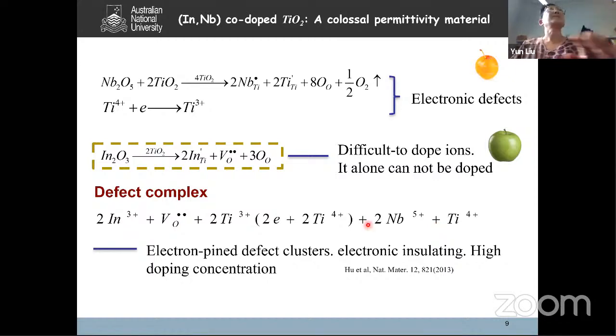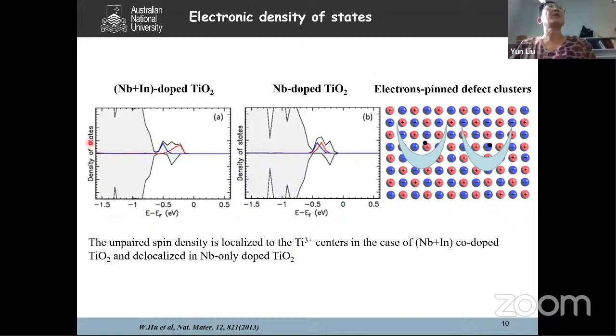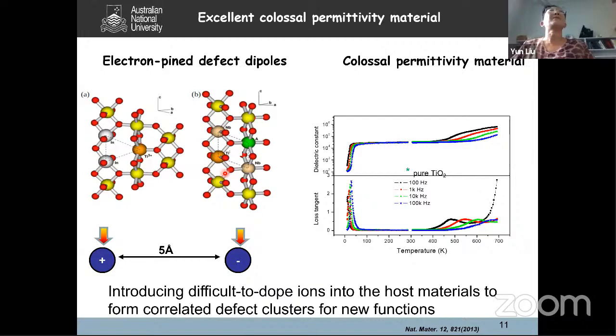Okay. Based on that, we found that if we use indium and niobium to create an environment to take the indium in, we form the co-doping, so the electrons are localized. If you have only niobium doping into titanium, the electrons come from titanium reduction and are delocalized. In this co-doping case, the electrons are trapped within these big defect clusters. So these electrons can move around within this 7, 8 octahedral range, roughly about 5 angstroms. So in that case, electrons are pinned, localized in this range.